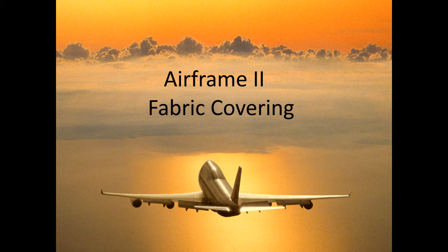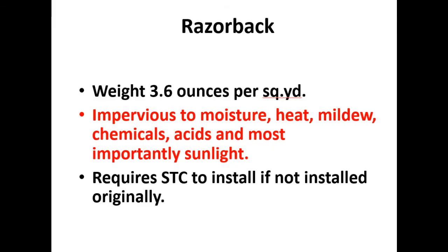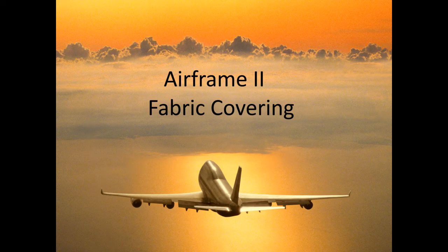Razorback is the fiberglass option at 3.6 ounces per square yard. The great thing about Razorback is it's impervious to moisture, heat, mildew, chemicals, acids, and most importantly sunlight — UV rays are rough on fabric coverings. It requires an STC to install if not originally installed.